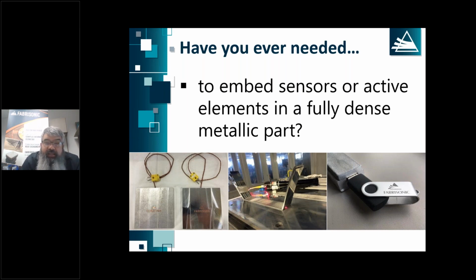Ultrasonic welding is not a new idea. It's been around since the 1960s. Early on, it was called wire bonding in the electronics industry. What we've done is taken that 1960s technology that used maybe 50 watts of power to weld small wires in electronics, and we've scaled that up to about 10,000 watts so that we can weld thin films layer by layer to produce three-dimensional shapes. The beauty of using ultrasound is it's a solid state process.